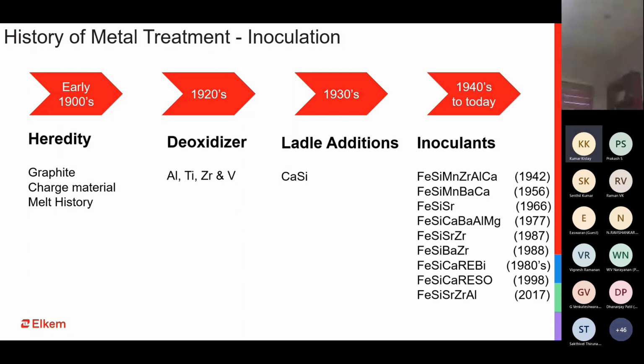So the 1940s was the beginning, especially 1942 to be precise. We saw the first zirconium and manganese based inoculant come into the picture. I believe we would definitely have some of the members in the audience today who have been using SMZ inoculant. That's a silicon manganese zirconium inoculant from Elkem, or maybe it can be a similar composition of an inoculant from a different supplier. Because zirconium manganese is a very common inoculant even today. That was the first proper silicon based inoculant which had come into the picture in 1942.